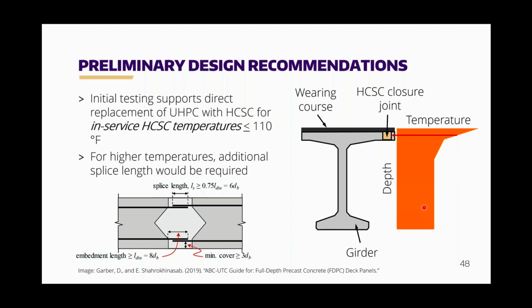And that's because at some point you're going to get close to that glass transition temperature and things are going to become more rubbery. For higher temperatures, it's not to say that you couldn't use HCSC. It just means you need to think about increasing your splice length in order to accommodate those higher temperatures. And of course, when you're thinking about this material and its structural use, you really need to consider the temperature where the joint is in your structure, which is a different consideration than you might be used to.